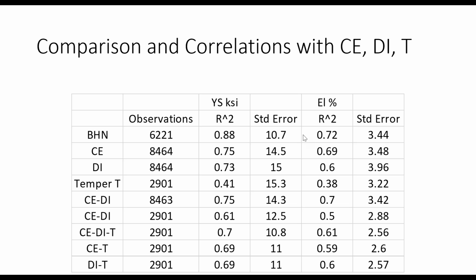For elongation, it's 72%, or 0.72 as a fraction, and 3.44. You can see that I'm not very close to the line, even though I have a higher correlation coefficient when I have this large data set. I get the poorest standard error, even though I get relatively high correlation coefficients. With tempering temperature, I only get 41, but I am only 15 KSI typically away from the line.